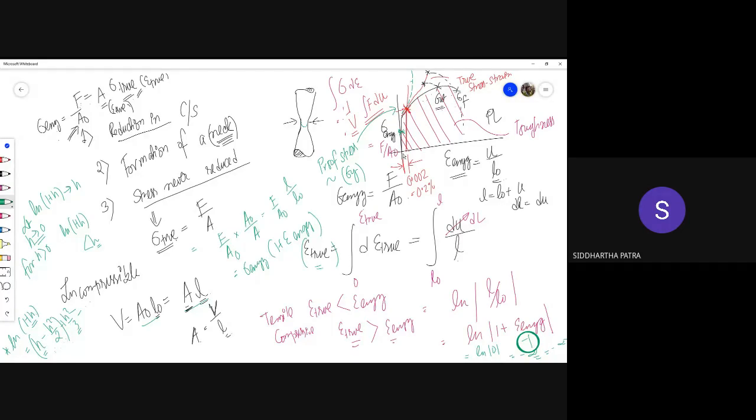Then you would end up detecting any point on the elastic part of the stress strain diagram. So that's why you need a finite, non-zero but very small value of plastic strain for detecting the representative, within quotes, yield stress value. And proof stress is that representative yield stress value, and that tiny value of plastic strain that you take is 0.002, and draw this line parallel to the elastic part of the curve.